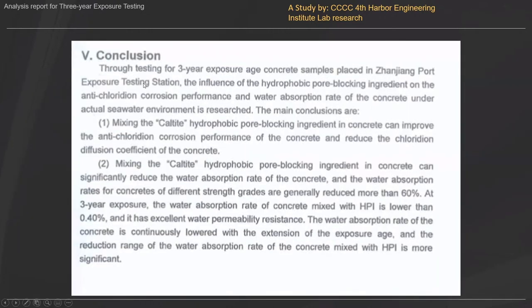The conclusion here, after testing for 3 years: the samples which contain the hydrophobic ingredient show a massive improvement in corrosion performance and water absorption. Mixing the HPI ingredient in concrete can improve the anti-chloride corrosion performance of the concrete and reduce chloride diffusion through compaction of the concrete. Mixing hydrophobic polymer ingredient in concrete can significantly reduce the water absorption. So this is after 3 years testing, and in the HPI environment, the actual measured absorption was 0.4, even after 3 years in that environment.